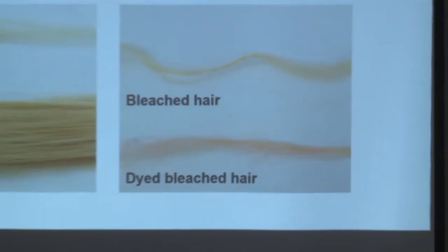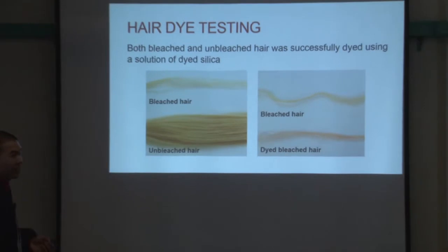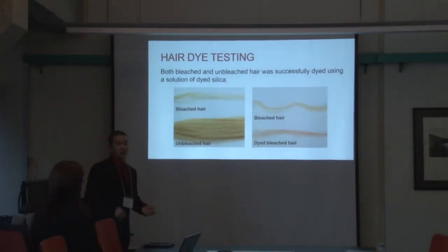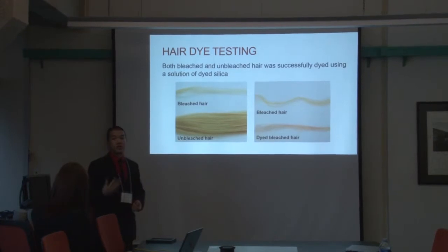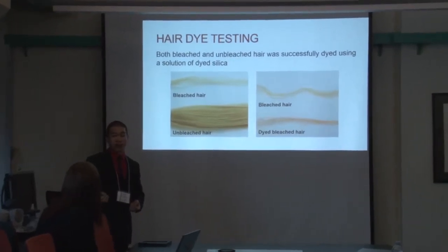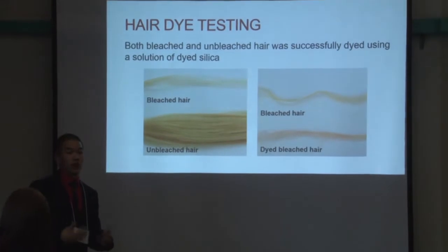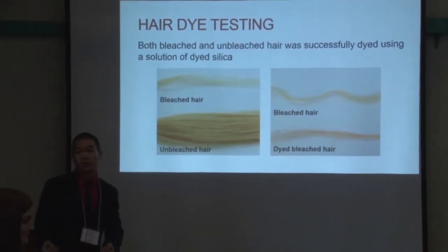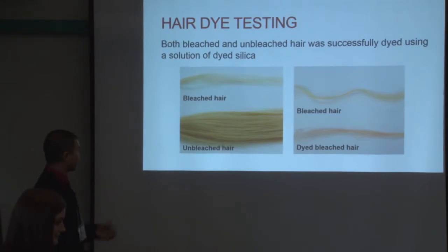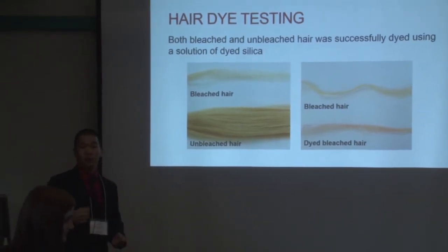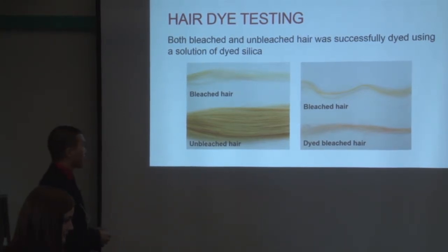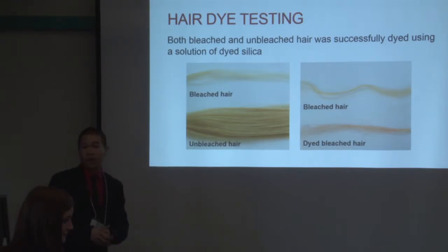So once we have our particles, the next logical step, because we're making a hair dye, is to dye our hair. We took our particles in solution, because once we calcinate the particles, they might experience an irreversible agglomeration, which is very hard to separate even after sonication. So we decided to keep it in solution for easy processing. We submerged a sample of human hair, which we got online. It's actual human hair. We submerged it for about an hour. Then we took it out and washed off the excess particles that were superficially attached on the hair. So here you can see the results.